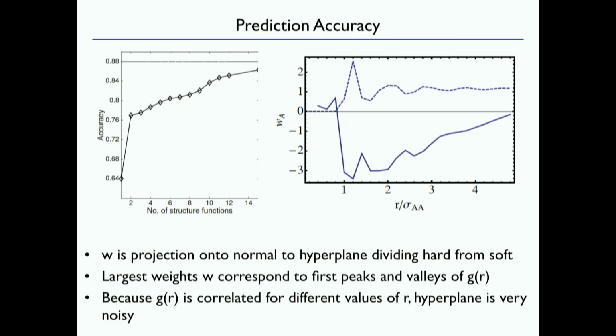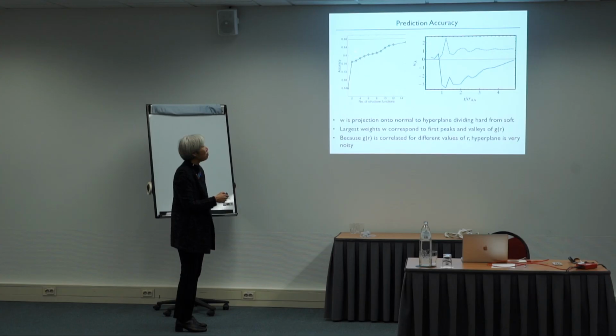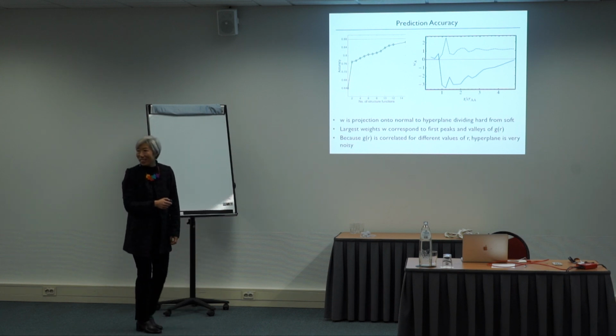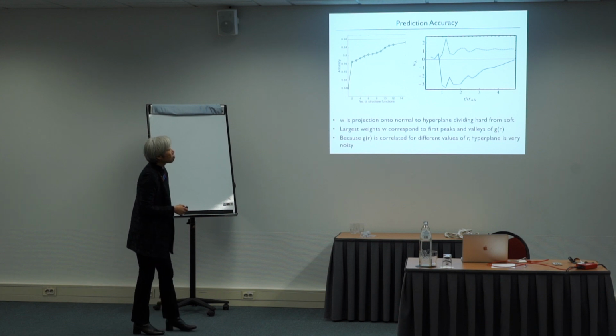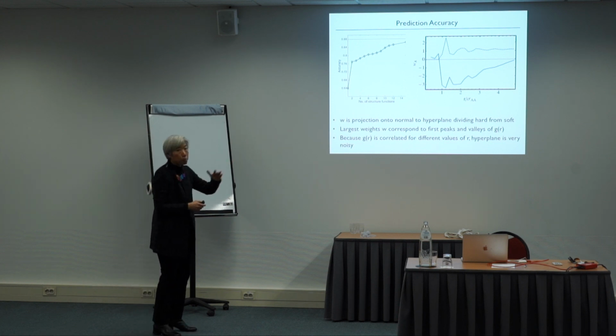So it's really mainly the height of the first peak. It turns out you can now go back and look at the hyperplane and ask, how many structure functions did you need? If I just have the height of the first peak, just g_AA, that's 64%. If I use two, the first peak of g_AA and g_AB, I get 76%. Then I just get a slow increase after that. And what are the important things? You can look at the weights in the hyperplane, to see which variables are weighted most strongly.